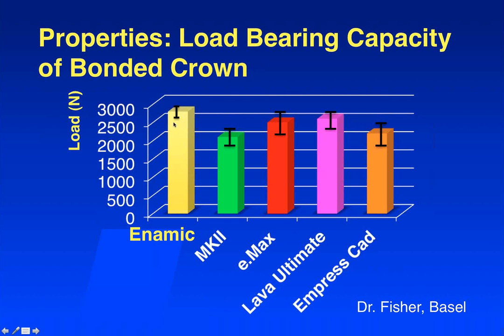So if we look at this test, the Enamic is yellow, Emax in red, Lava Ultimate in the pink. Essentially, when you do the statistic analysis, basically these are all the same. The Enamic did have the highest mean strength, load to failure, but if you do the stats, because of the spread in these other materials, essentially the statistics show them to be all the same. Mark II was lower, and so was Empress Cad.